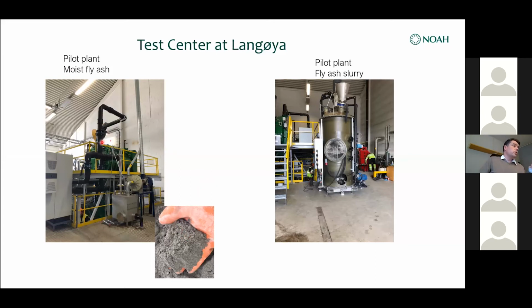The positive side also here, you don't need a lot of water cleaning because you just add enough water to make the fly ash moist. So it's a dry process and fairly simple. To the right here, we have another process where we do the carbonation in a slurry. The kinetics in the slurry is much slower, but we have invented a system where we make a huge area of the bubbles such that at least the kinetics of the carbonation is acceptable. Here, obviously, we have to clean a lot of water, but the good part is that we can separate the salts from the carbonated fly ash just with a press filter. So it's easy to combine with our salt project.